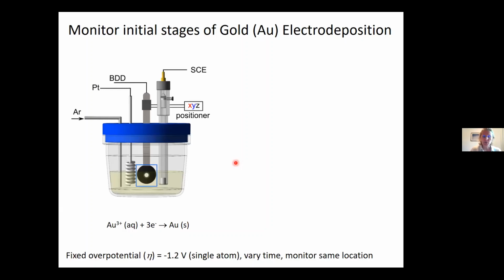Gold is quite a simple metal system to deposit, it hydrolyzes nicely, but we really wanted to look at what's going to happen at these initial stages using this concept of identical locations, so that we can go back to the same area each time. And our locator points are actually, when we cut a hole in that diamond, it has a very unique structure. And actually it was surprisingly easy to go back, much easier than we and our electron microscopist colleagues found, to go back to exactly the same area.